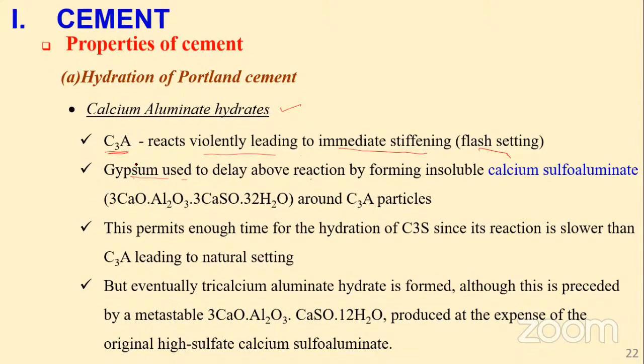So what happens is that gypsum, instead of tricalcium aluminate reacting, gypsum will react with the aluminate to form calcium sulfoaluminate. So instead of the tricalcium aluminate just coming into contact with water to form calcium aluminate hydrate, because that will lead to flash stiffening, flash setting, an intermediary substance is formed, calcium sulfoaluminate. And this is going to coat the tricalcium aluminate particles. Remember, in a cement, let's say this is a container, and this is our cement.